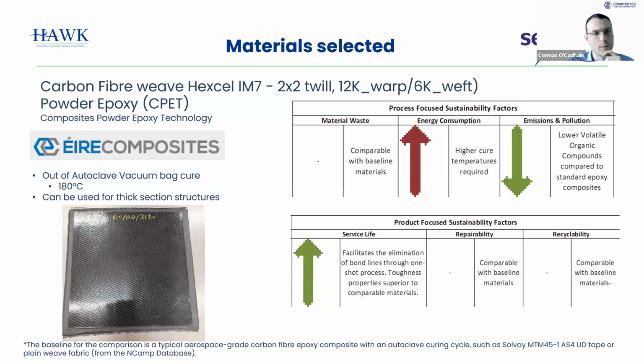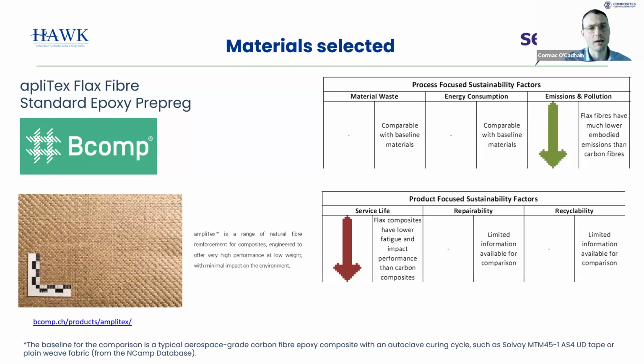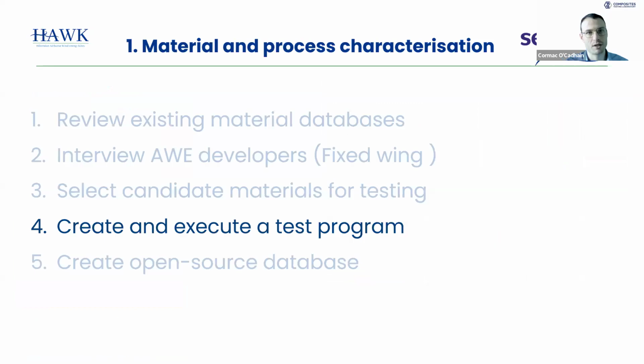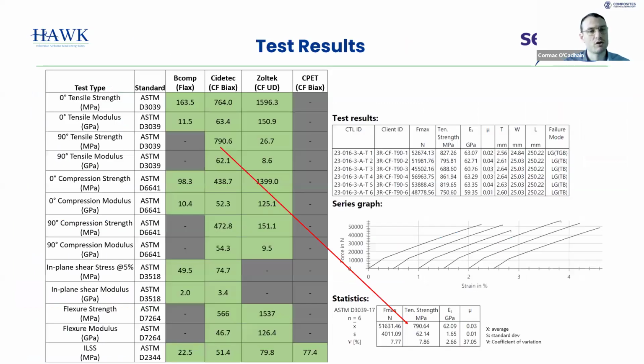Another material we looked at was this powder epoxy, or CPET, developed by ÉireComposites. So this is a powder epoxy, less emissions from this material when you're processing it, and the products. So it facilitates, because they can be cured, parts can be co-cured with this powder epoxy, so you can reduce the need for bond lines in the parts, so that improves the service life of the parts. And then we looked at a flax fiber, and this has less emissions and less embodied energy required in producing these parts, more sustainable. So the test program itself, so this is basically the test matrix, all the tests we conducted.